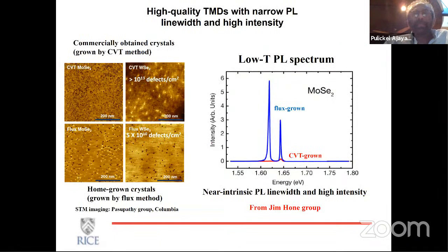And again, it's very clear that depending on the way you grow them or the process that you use, the density of defects can be quite different. This is not our work, but it is from Jim Hone's work at Columbia. We were actually part of a joint work. It shows that one could tweak the growth technique to decrease the defect density significantly. And this is very important, finally, if you want to use them for semiconductor device applications.